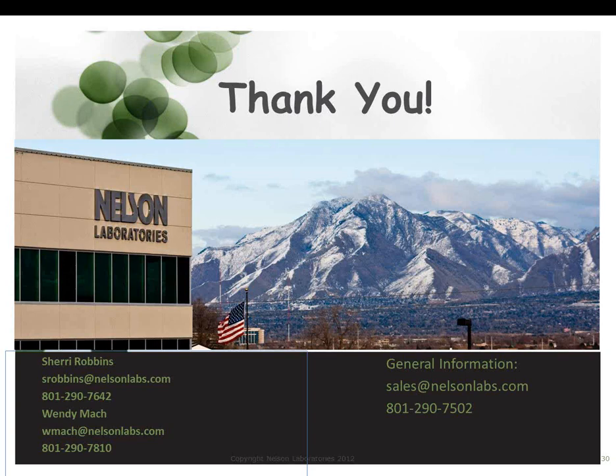The next question that I have is, when aging is performed without product, what is an acceptable percentage of degradation on the material that could be considered stable? That's the purpose of the aging, is to evaluate the package over time using the test methods. So determining an acceptable amount of degradation really isn't part of the testing that's designed around that. Usually what happens when you do the aging is you take the samples that are post-aged and run them through the dye migration test or the seal peel tests. What we've seen, if you're looking at seal peel tests, is that a lot of times the seal will actually get stronger over time rather than weaker. So those tests really aren't indicators of degradation.